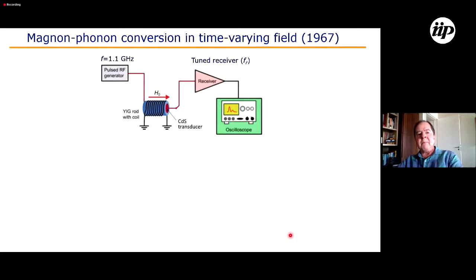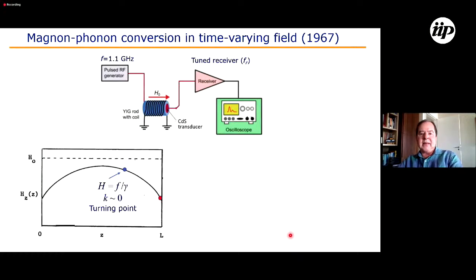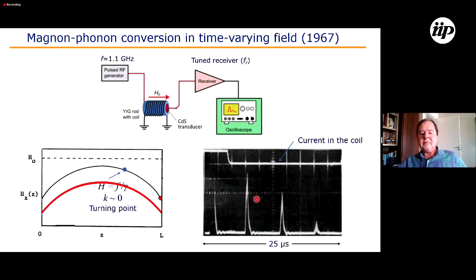One can also convert magnons into phonons by the time-varying field. We use the same experiment as Strauss, but while the pulse is propagating, we pulse the magnetic field down like this. So when the elastic pulse returns to this point, there is no turning point. So the elastic pulse goes to the other side, bounces back and forth, just as an elastic pulse, because we have suppressed the turning point, and there is no conversion back from phonons to magnons.